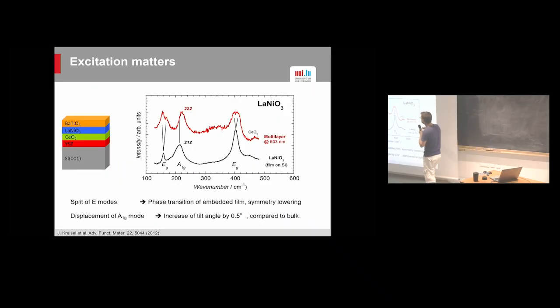So this would be a comparison of, say, pure lanthanum nickelate, as in a thick film, and the lanthanum nickelate in the multi-layer. Okay. So overall, it corresponds pretty well, except that you see this E mode. The E mode's representation, of dimension 2, splits into 2 modes of dimension 1. Okay. So this indicates that there is a phase transition happening in the lanthanum nickelate layer. The A1g mode, with a representation of dimension 1, doesn't split. I mean, it can't. It already has dimension 1 only. It shifts a little bit. Well, by 10 wave numbers, so that's not completely negligible. And this E mode splits as well.